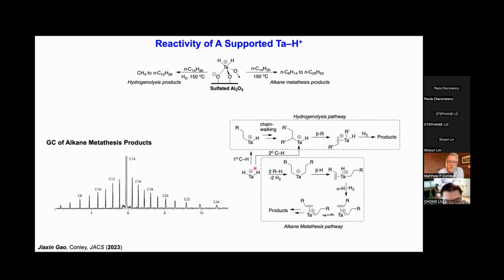So for the hydrogenolysis pathway, we think we're probably going for a primary CH and then undergoing chain walking to that eventually undergoes statistical beta alkyl elimination and subsequent hydrogenation to give us our products. We can't currently rule out direct CH activation of a secondary carbon, but when I see this from the alkane metathesis reactions, that suggests to me that there's a lower barrier to activation of the primary CH3 group compared to the secondary CH2, which I think is totally reasonable based on everything known about sigma bond metathesis reactions.